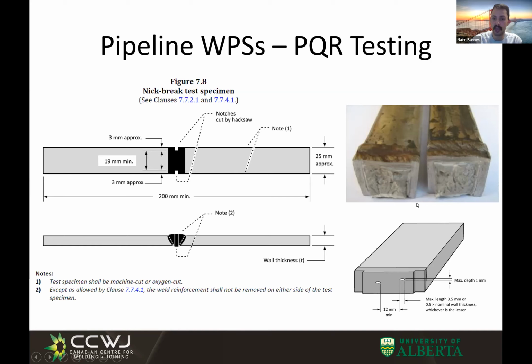And then really what they care about for a nick break test is examining what that fracture surface looks like, right? Did the failure happen more to one side than the other? How much of that weld material is left over? Did it break somewhere else that wasn't in the weld? All of those things start to matter, and all of those parameters and acceptance criteria are clearly listed within the code.